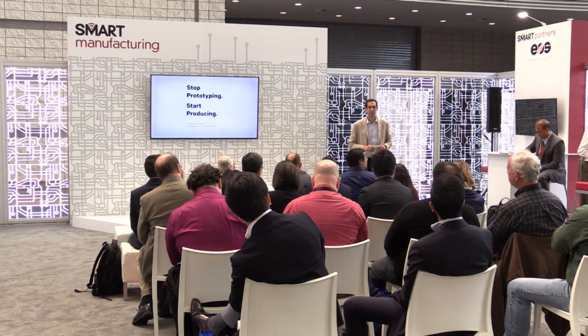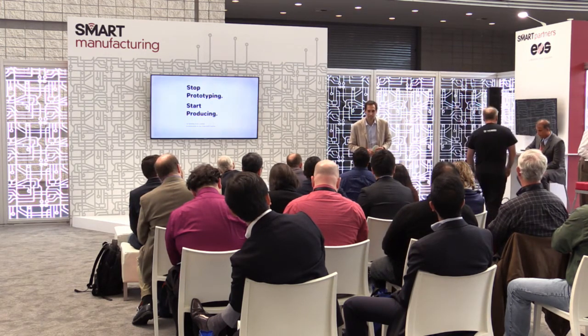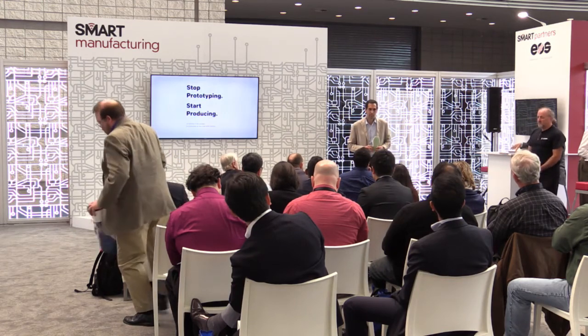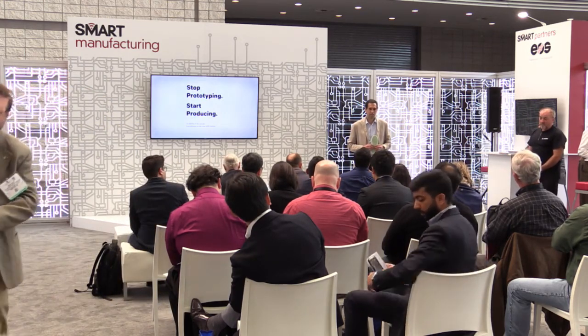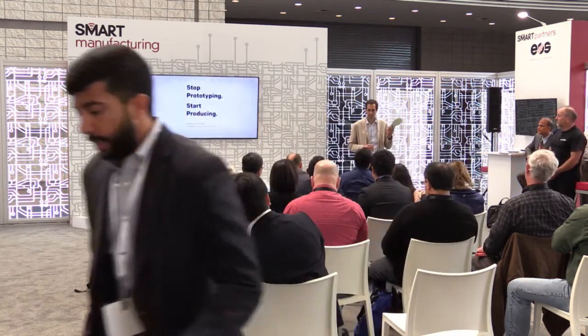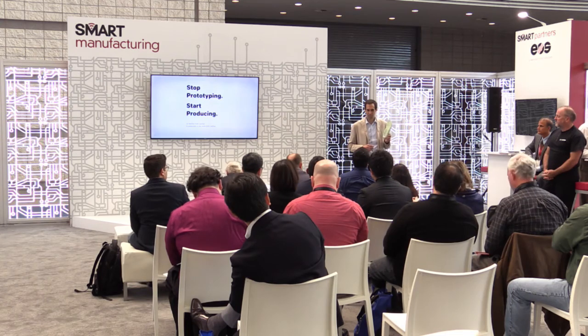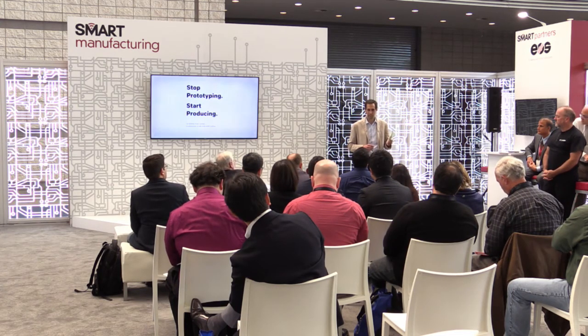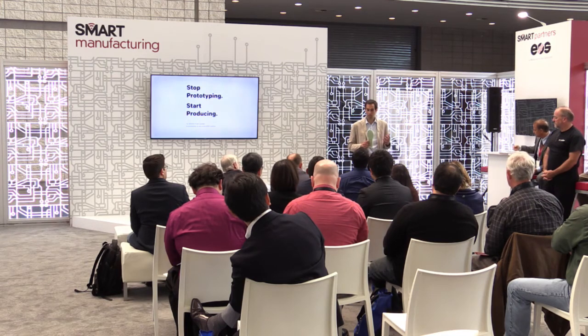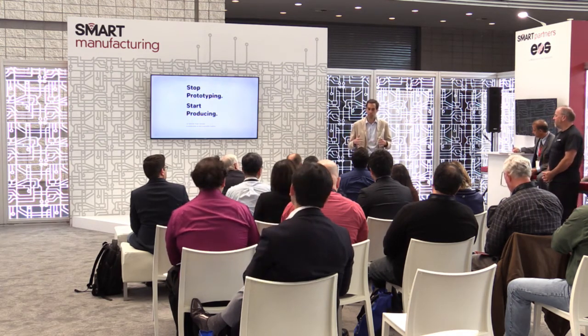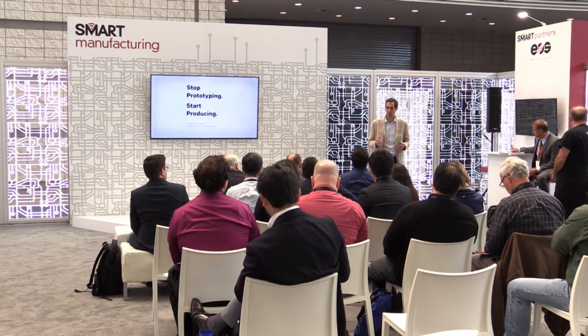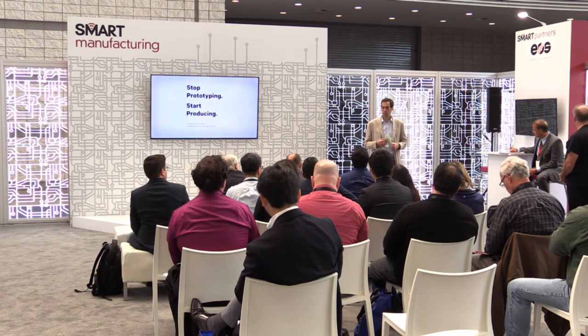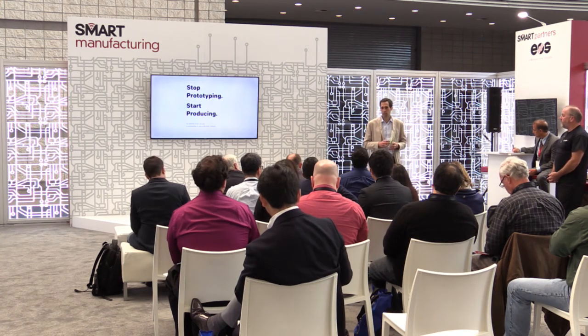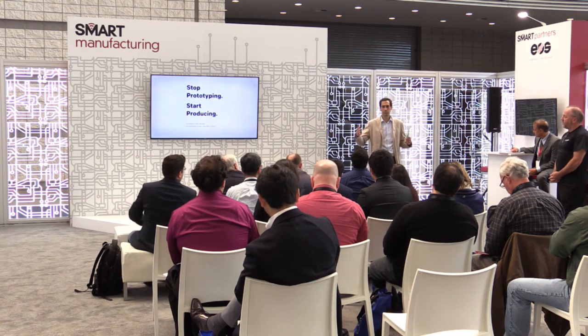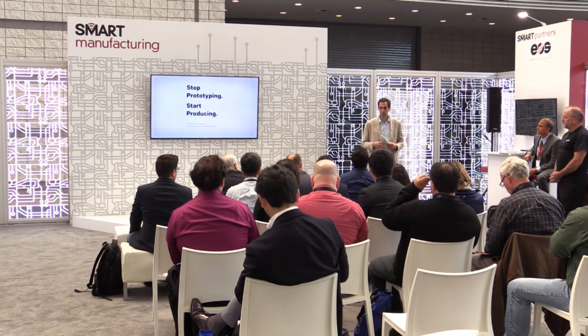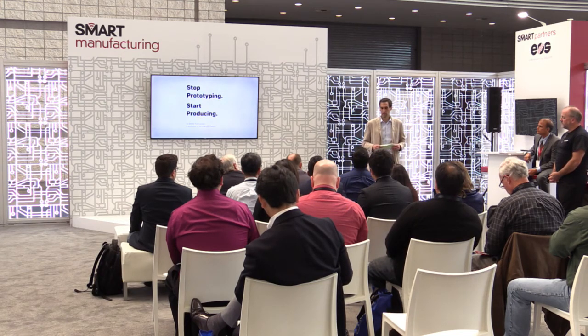Yeah, there's a question up here. How resistant to oxidation, moisture, and UV effects are the materials? Because I'd imagine the midsole gets exposed to all of them. Absolutely, yeah. So we had to meet all sorts of standards for moisture absorption and UV stability in order to meet the needs of Adidas for the midsole. Different industries have different requirements and different materials have different requirements. But in general, the materials don't fade under light. They're quite stable, especially when compared with, say, other SLA resins. But if you're looking at, say, the UV stability required for automotive and being able to survive Florida humidity for 5 years, we're not quite there yet.